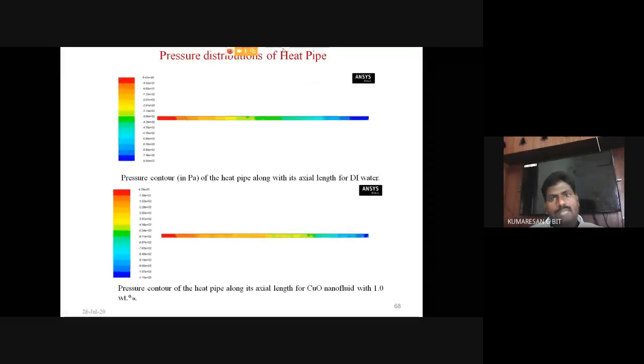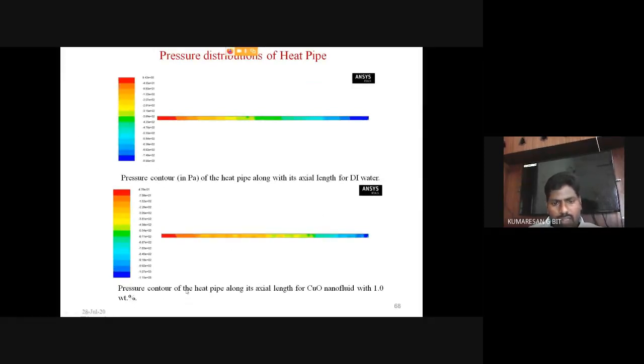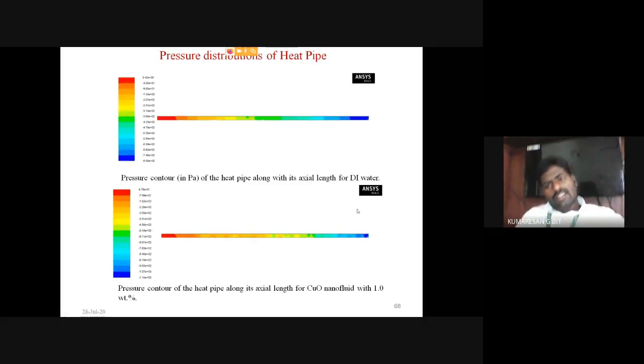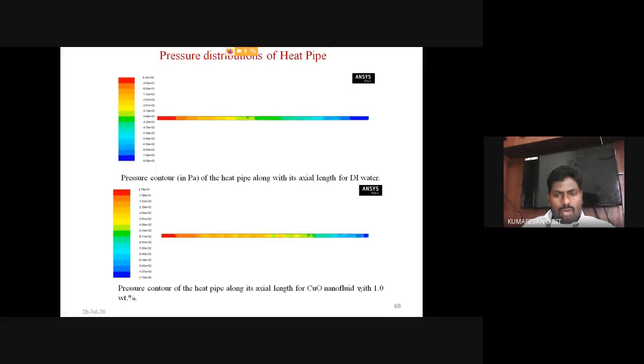Okay, then the pressure distribution of the heat pipe. Then the pressure contour of the heat pipe along its axial length for CuO nanofluid, and for DI water and 1 weight percentage of the nanofluid, both are shown here. You see here the pressure distribution for the 1 weight percentage of the nanofluid is somewhat low compared with that of the normal DI water filled working fluid heat pipe.